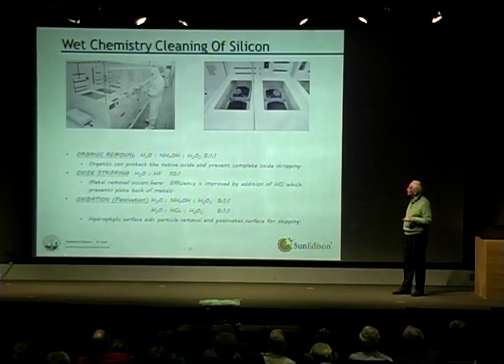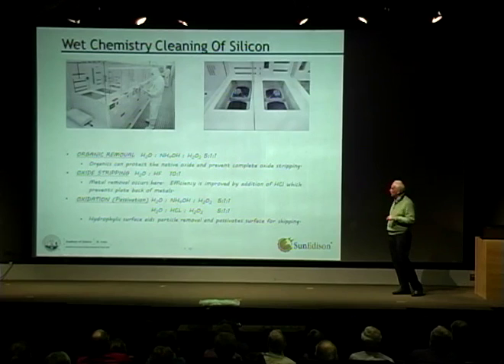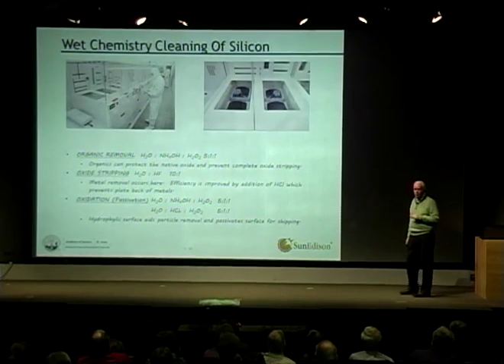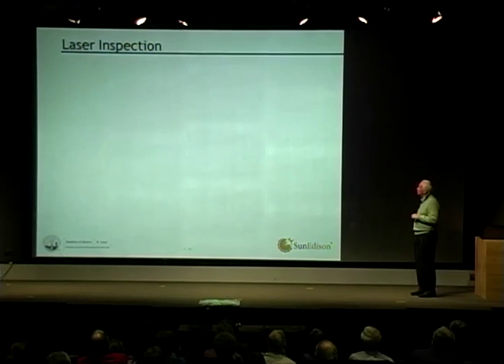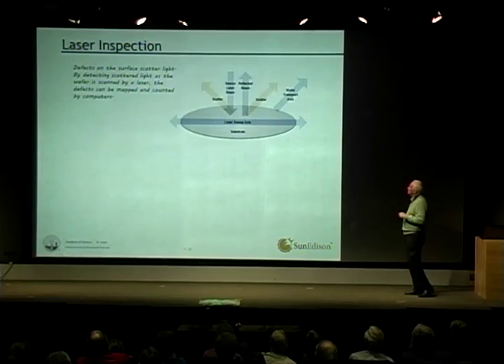We go through some cleaning. There are various steps. I can explain this to people later if you're particularly interested in cleaning. But basically, we remove any organic contamination with these chemicals, and then we remove any oxide on the surface, and then we re-oxidize it with a clean, stable oxide so that we can ship it safely. So that's getting rid of all the metallic contamination and so forth, and also removes particles that might be stuck on the surface. And then we go into this laser inspection mode.